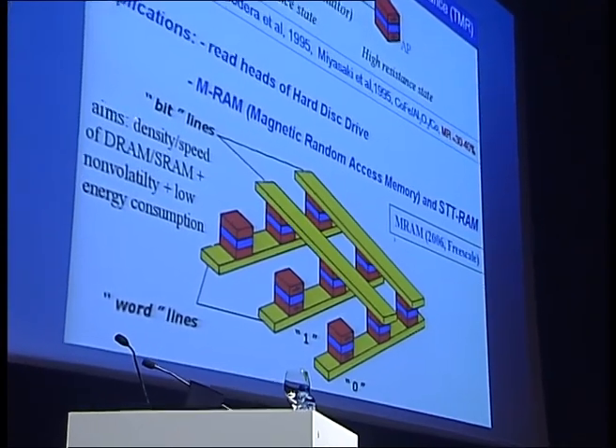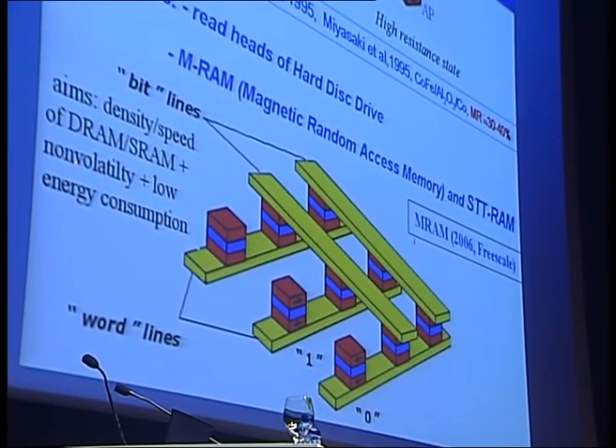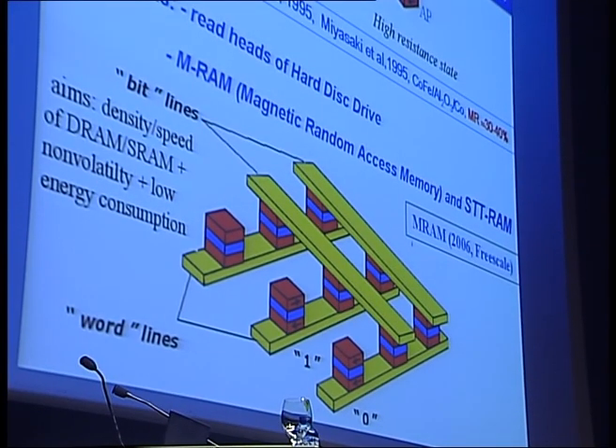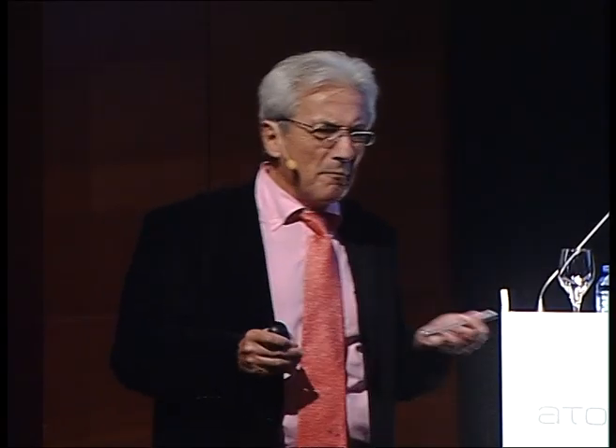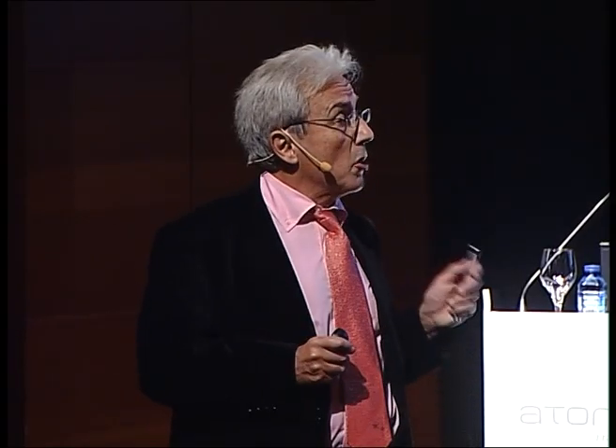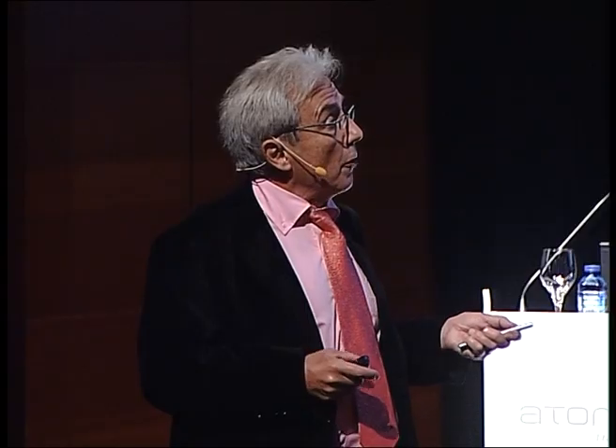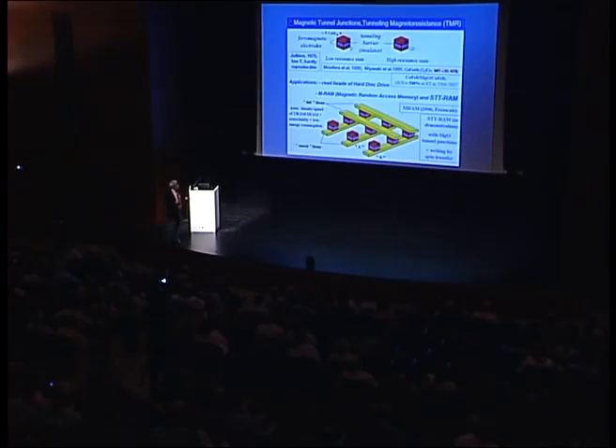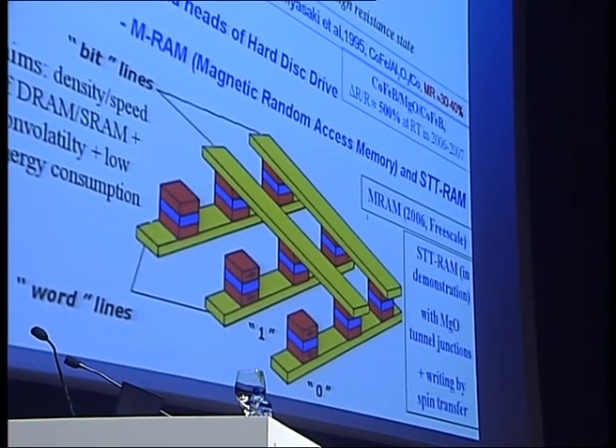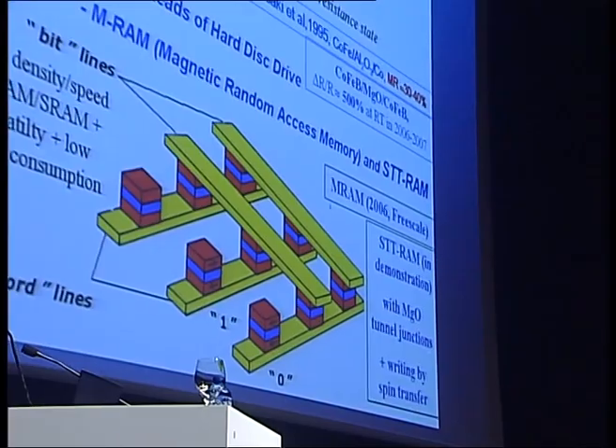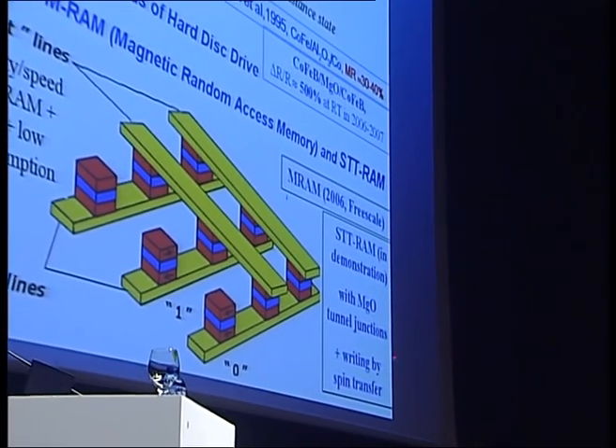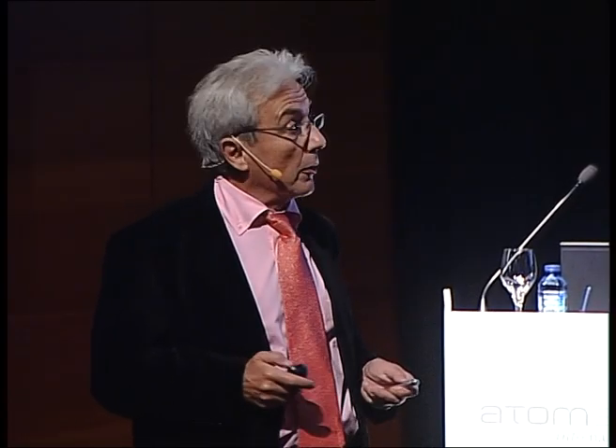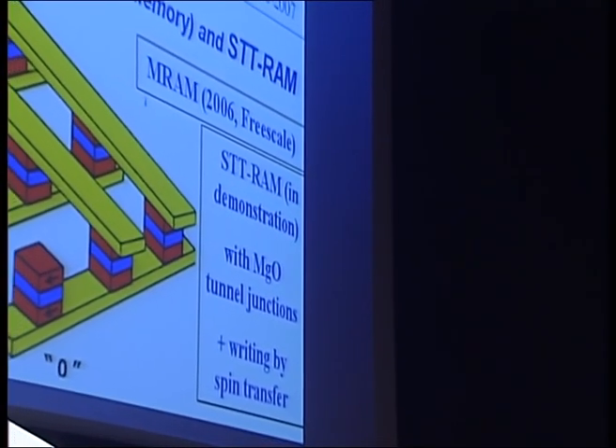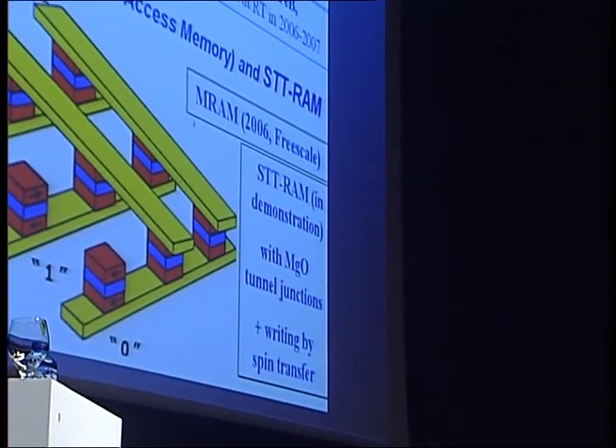And so this is the objective: having the density and the speed of the RAM, plus the non-volatility and certainly low energy consumption. The first generation has only a small impact on the technology of the computer, some impact, but small, but much more is expected from the next generation of STT-RAM. The difference with the STT-RAM in development in many companies in the world is that they will use the recent advance on the tunnel junction, a much larger TMR ratio, and also the writing by spin transfer, simply by transport of magnetization by electrical currents. And so I will come back to the spin transfer, and I will say a few words on the MgO tunnel junctions.